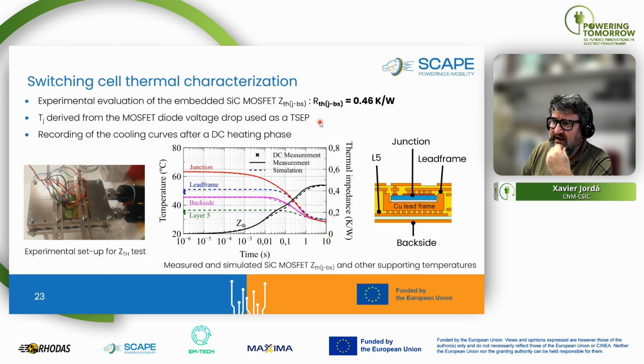In our case, this parameter was the embedded MOSFET diode forward voltage drop. Through this thermosensitive electrical parameter, we are able to measure the junction temperature during the cooling phase of the switching cell after a steady state dissipation phase. From this cooling curve of the junction and also the backside temperature of the embedded MOSFETs, we can obtain the final thermal impedance curve, which matches very well with the expected theoretical values obtained by simulation, 0.46 Kelvin per watt.